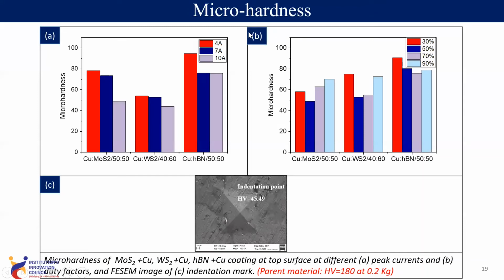The micro hardness machine. This is the micro hardness that we have obtained for different coatings. So you can see a very low hardness obtained by using the lubricant powder. Although for the parent material, which was mild steel, we observed hardness was 180 HV at 0.2 kg load. But for solid lubricant, you can observe a low hardness below 180, that is 80, 60, 80, 65, 67. We obtained different hardness values.